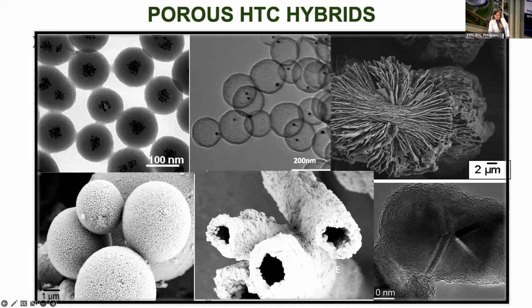For example, these are some platinum nanoparticles supported on a glucose-derived carbon. It's a one-step process: take glucose, take platinum chloride, throw them in an autoclave, and the glucose will reduce the platinum chloride to platinum nanoparticles that deposit in the middle, where you have a more hydrophobic core of this carbon material with more hydrophilic groups on the side. You can combine this with templating, so you could put one platinum in the middle of each nanoparticle, or, as in these tin oxide nanoparticles that you throw with glucose in a reactor, you self-assemble the tin oxide with carbon in spheres, and there are many other examples that I can give you. So it's very nice for making carbon and carbon hybrids.